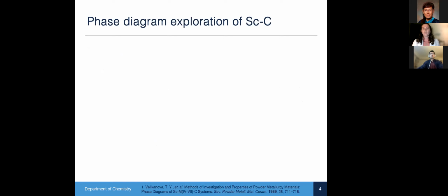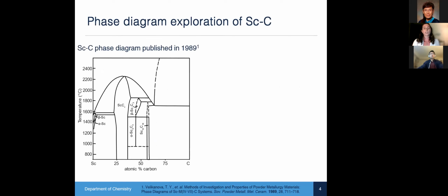So the phase diagram of the binary scandium carbide composition is relatively old. It was published about 30 years ago, and it still currently has 3 different phases. We have 2 compositions that have stoichiometries of 4 to 3 and then 15 to 19. And then we have one, which I'm showing here, which can incorporate different amounts of carbon vacancies into an NaCl type cubic structure. And so it would be within this area that we would find a more ordered layered discandium carbide.